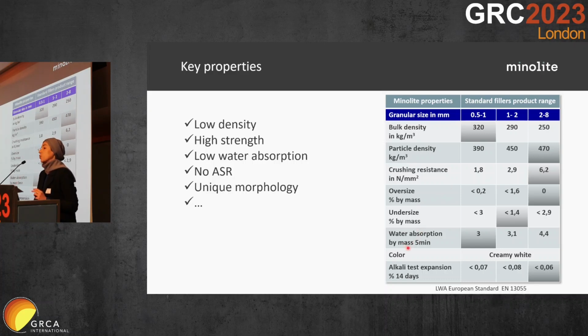And the other thing is the water absorption. Water absorption is very low. This is unexpected in a porous structure, because porous structure is responsible for high water absorption. And high water absorption is not desirable for a superior quality concrete. But Minolite has a special coating that not only seals the pores on the surface, but also keeps the low density.